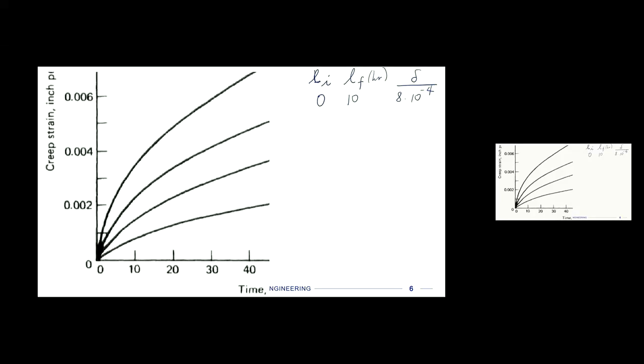Okay, so how do we calculate where we start the next one? Well, we come up with a factor, which is the life we would expect for the next level we're going to, divided by the life we would expect for the level we're at.